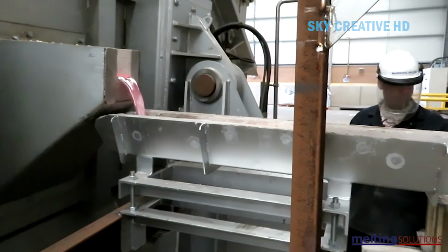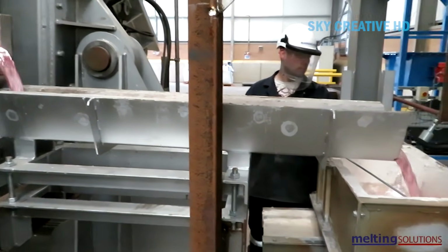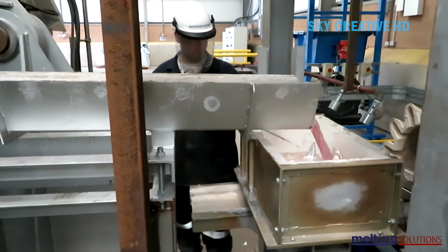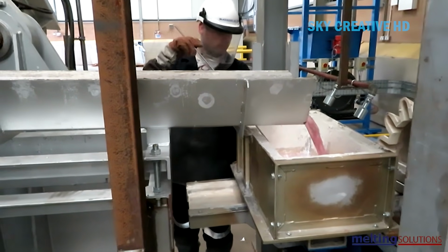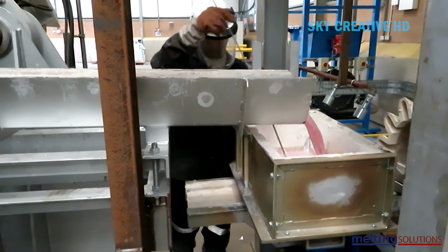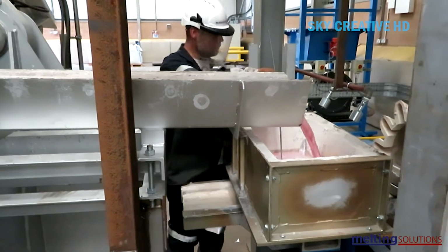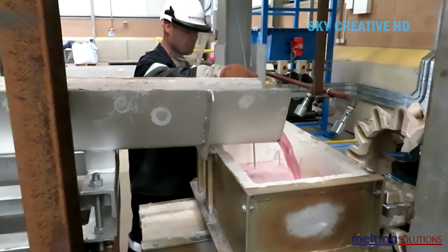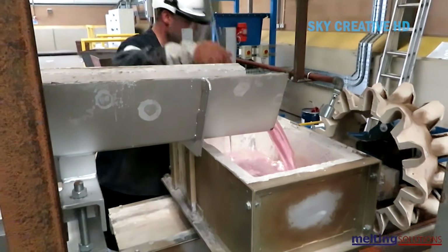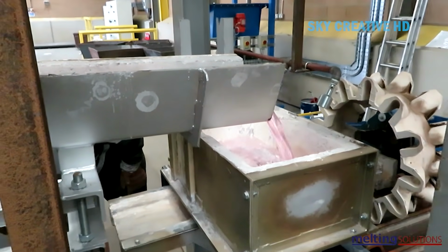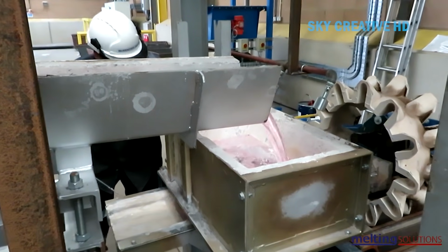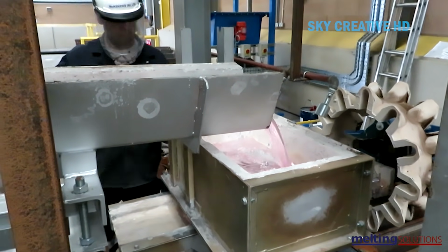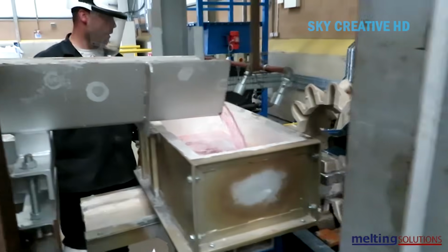Rotary furnaces are particularly well suited for processing mixed and contaminated scrap because the rotation keeps the melt churning, which promotes even temperature distribution and helps burn off surface coatings, paints, and other organic contaminants. The tilting mechanism allows operators to pour the molten metal precisely when the melt is ready, without having to move heavy ladles around the floor.